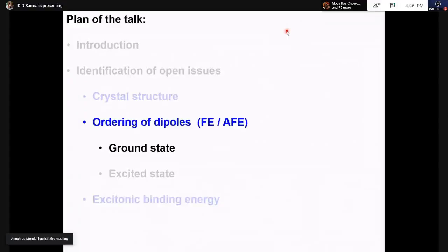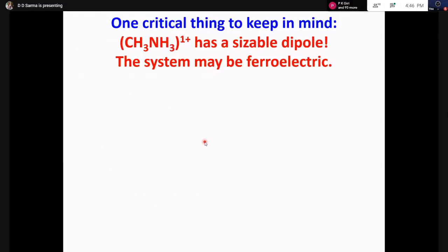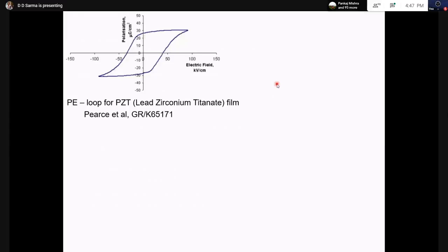And so we started asking directly the question, let us try to sense what the dipoles are doing. Now, in order to understand what the dipoles are doing, what we looked at is directly, if it is ferroelectric, let us ask what ferroelectricity is characterized by. Here, what I'm showing you is the polarization of a ferroelectric material if I apply an external electric field and sweep the electric field. I start with zero electric field. On the x-axis, I'm showing the applied electric field. I apply the electric field up to something like 100 kilovolts per centimeter. I reverse it, go to minus 100 kilovolts per centimeter, and come back to zero.